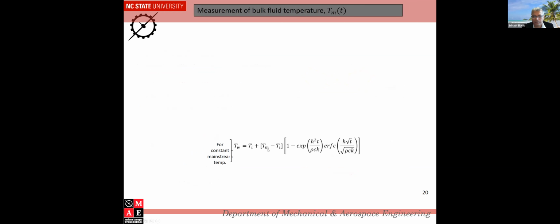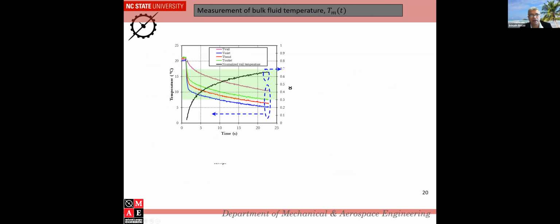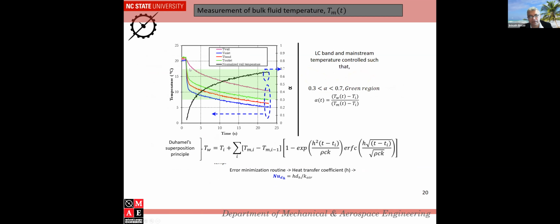So this is how our experiment looks. If our mainstream temperature was constant, that means the air temperature in the experiment remains constant, then this is the equation we use. But in our experiment, we find out that the air comes in at 20 C and goes down, and every location has a different temperature response. So we take into account all of this using the Duhamel superposition integral, where we divide this into hundreds of time steps and calculate every time step to account for the slope of this temperature change. So if a color change occurs in 5 seconds, this is the amount of slope you would take. If it occurs at time 20 seconds, then this is all the information you would take. That is how we calculate the heat transfer coefficient to make it more accurate, and we can get it within 6 to 8% uncertainty.